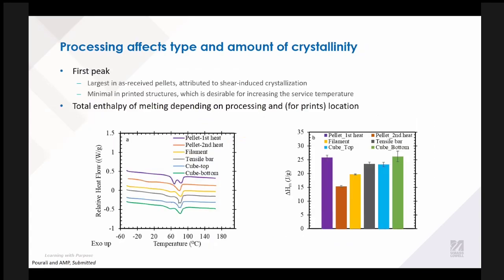We've seen that our processing and our locations can affect the type and the amount of crystallinity. So our as received pellets start in this purple bar with relatively high crystallinities. When we fabricate our filament, we see less crystallinity. In our tensile bar, we recover some of that crystallinity.